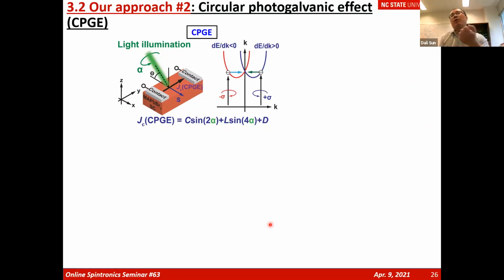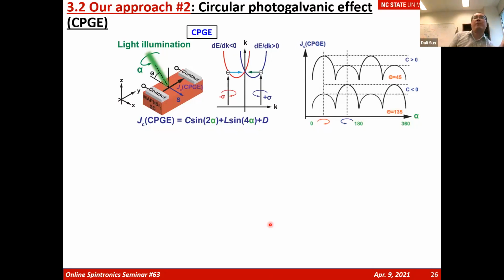By absorbing circularly polarized light, one spin direction will be popped out into one subband. Because of spin-momentum locking, the group velocity for that spin-dependent photocarrier has a positive value. If you excite the same surface using left circularly polarized light, you excite to the negative k-space and give you the opposite sign of photocurrent. So by tilting the incident angle from positive to negative, you will observe the oscillation of the photocurrent as a function of circular polarization. That's direct evidence for the formation of a split state, because everything is measured without an electric field. The only electric field is because of the momentum of the spin once excited by circular polarization.